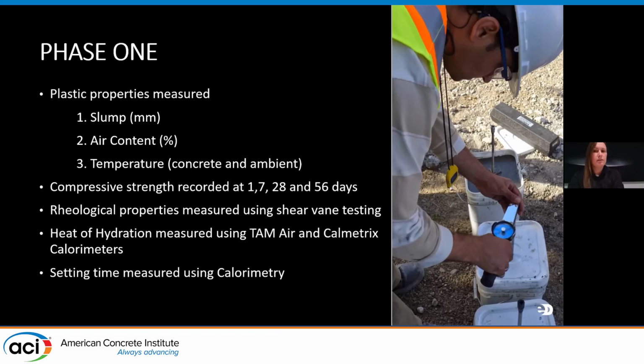So what were we looking for in phase 1? We tested 26 different shotcrete mixtures to select the best performing mixtures to run through the shooting process. The mix designs were tested against each of the 3 ready mix suppliers' baseline control mix, with very tight temperature limits, large elements, and being restricted to a high volume of cementitious content. We knew we had to make a 70% slag mix work, even though it hadn't really been done before.